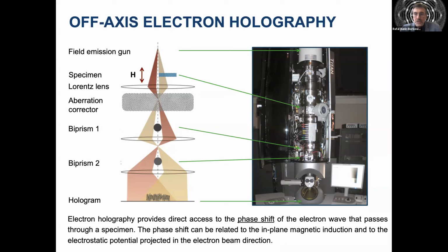If the electron source is coherent enough, especially if it's provided by a field emission source, then where the electrons that pass through the sample are overlapped with electrons that passed outside the sample, there is an interference pattern formed, superimposed on a normal bright field image of the sample. And this interference pattern is the electron hologram, which carries direct information about the phase of the electron wave. In other words, it solves the phase problem in electron microscopy, and it provides access to all spatial frequencies of the phase, including low spatial frequencies of the phase faithfully, in addition to providing a perfect energy filter in the electron microscope.